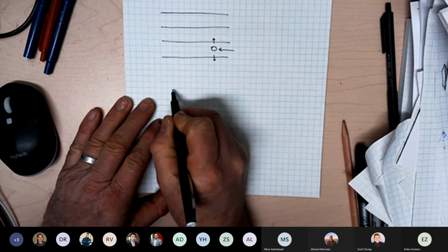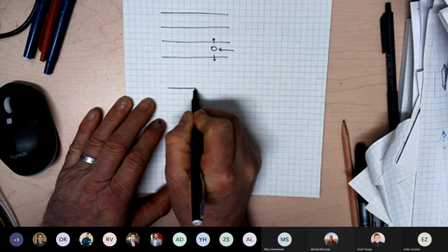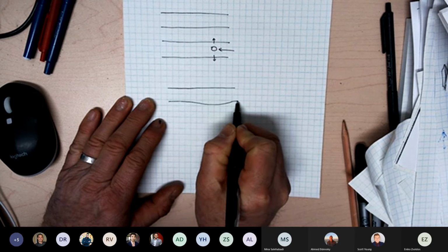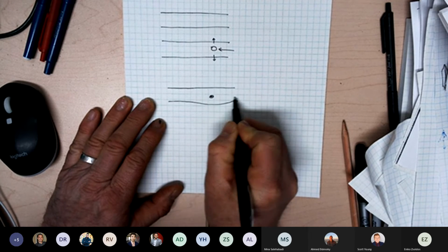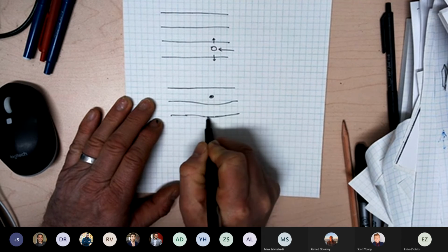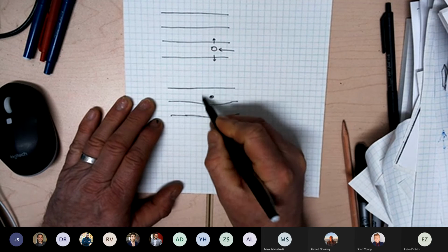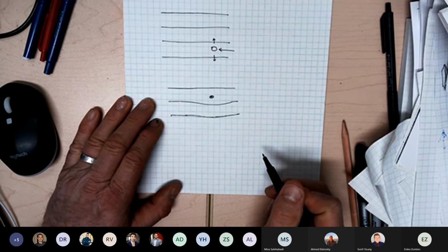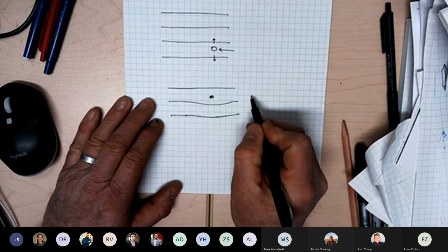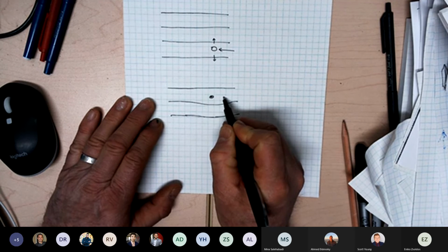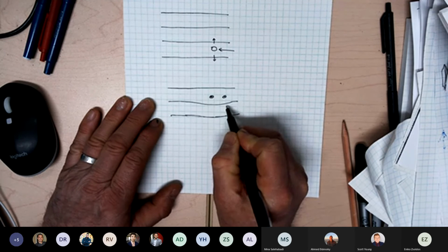So you have a situation like this, where the intercalant is in there, and it deforms the layers around it locally. So you made a bigger layer spacing here, and there's some strain energy required to do that. You have to actually strain the host lattice. So the next atom that comes along could say, look, if I go nearby, the lattice is already opened up for me.